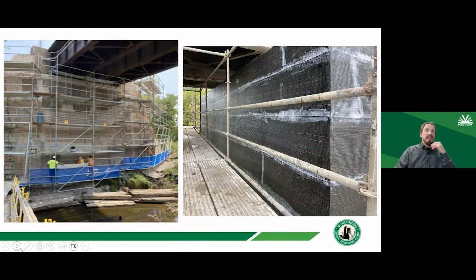However, that's in the process of the abutment over the river abutment there, right? So you've got all the reinforcing steel, shoot it back with shotcrete, and you're done. However, on the piers themselves, we weren't able to overbuild them. One of the piers was right on the roadway, so we had absolutely no room to add additional reinforcing and do an overbuild. In that case, confining those repairs in carbon fiber made the most sense, and that's what you're seeing on the right. They wrapped the piers in carbon fiber, detailed the edges with a paste epoxy to make sure that those edges don't peel.